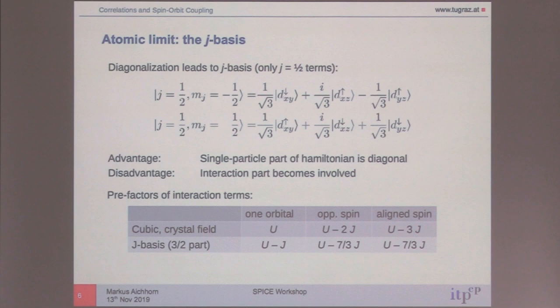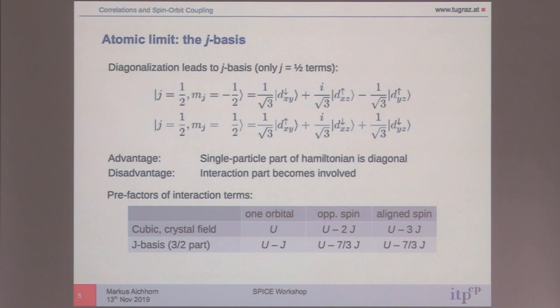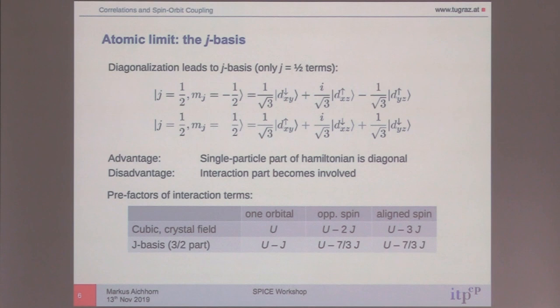A question from the audience: in your methodology, the crystal field is bigger than spin-orbit coupling for the materials in question — so there's no chance to neglect the mixed terms. The speaker clarifies: there are two crystal fields. One pushes the eG states out, and the other — which he was calling crystal field — is actually the splitting between the J subsets coming from lambda. If lambda is large enough, this separation is valid.